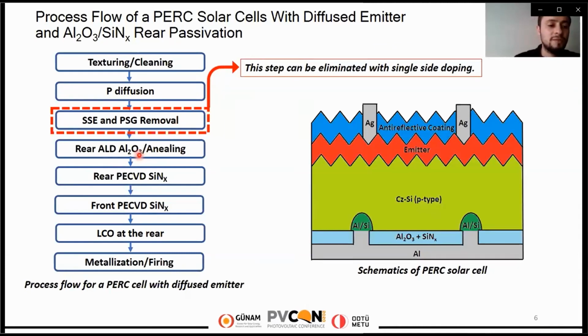The rest of the process flow will be the passivation of the rear side with aluminum oxide and anti-reflective coating at the front side and laser contact openings at the rear side. And finally, we perform metallization and firing processes.